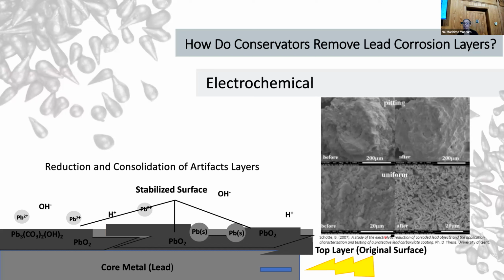You can accidentally deposit too much lead on the surface, for example, especially solid lead, which can have the effect of covering anything on the surface that you might have wanted to look at, like inscriptions or tool marks and things like that. So it does change the surface a lot. That is the one drawback to electrochemical cleaning. And so in the course of trying to clean your artifact, you can accidentally cover or destroy the thing that you're trying to save, essentially.